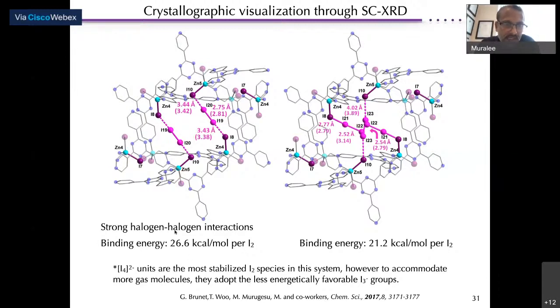And in this case, it is 26 kcal per mole of I2 molecules that are shown for these types of motifs. And you can see the X-ray data, and this is the calculated data in brackets in terms of bond distances. One interesting feature is, even though this is much higher in energy, the MOF is swelling. That means it's modifying its structure to accommodate even more iodine within the framework.